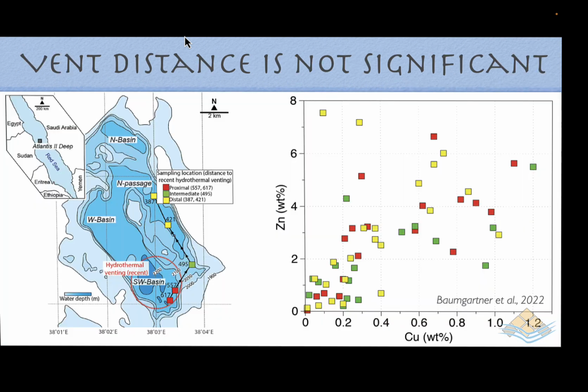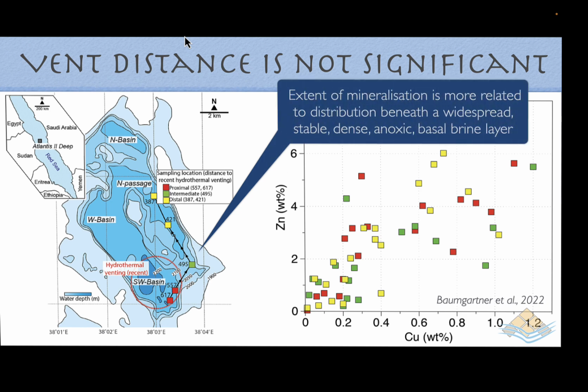If we look at the vent distance, the distance from an active hydrothermal vent, to the levels of copper and zinc in the sediment, we can see that vent distance is not a significant factor in the distribution of mineralization in these sediments. The proximal sediments indicated in red have the same range of copper and zinc weight percents as the distal sediments indicated in yellow. It's telling us quite clearly that it's not simple cooling that's causing mineralization in these brine pools.